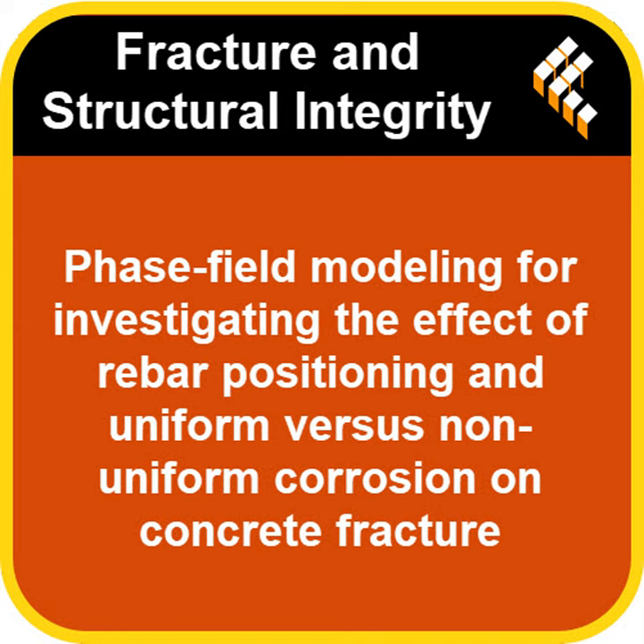What happened under uniform corrosion? With uniform corrosion, the interesting thing was generally they saw a single, fairly straight crack propagating out towards the surface. Didn't matter too much if it was one big bar or several smaller ones in these asymmetric layouts. Huh. And the amount of rust expansion needed to start that crack, they called it T1, and for it to reach the edge, T2, was relatively small. Okay, relatively straightforward. What about when they simulated that uneven, non-uniform corrosion with those same rebar arrangements? Here's where things got really different. With non-uniform corrosion, yes, they still saw main cracks going out to the surface.